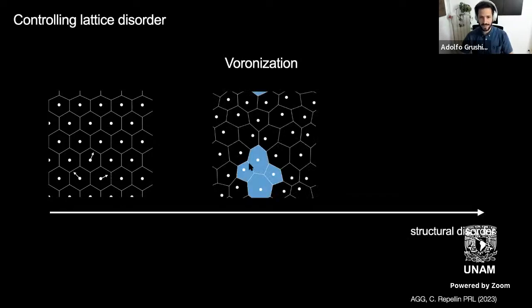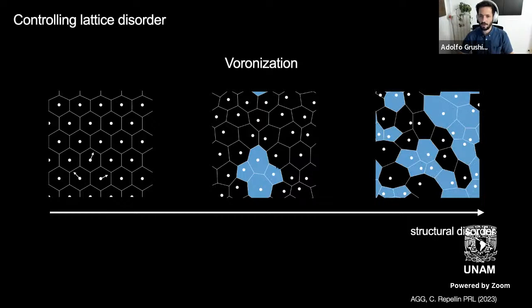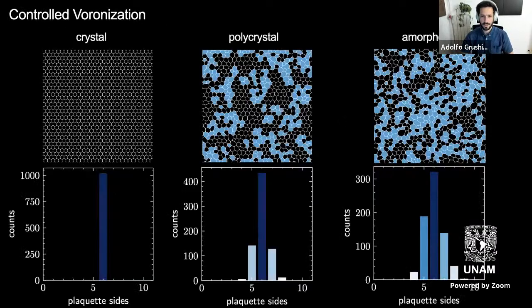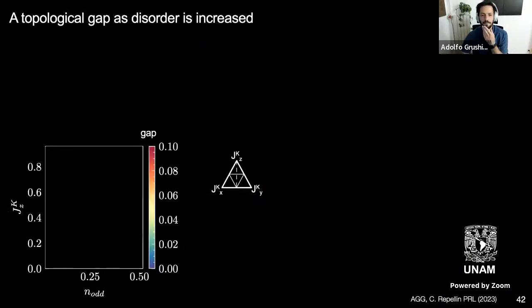you'll generate plaquettes that are not even in the number of sides. For example, here I have pentagons and heptagons. And if you keep going, you'll find more and more. By displacing the original lattice and then Voronoi-izing, you can continuously control disorder. This is what I show here in a bigger system, where you have only hexagons at the beginning, and you start introducing other plaquettes with different numbers of sides.